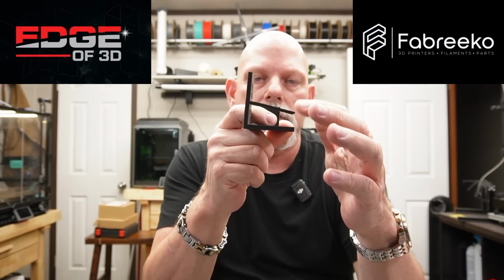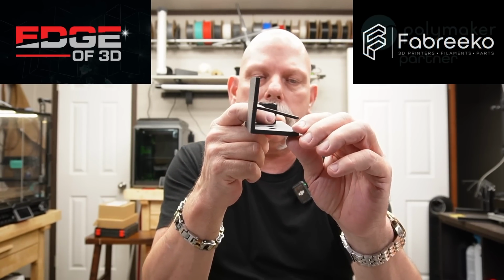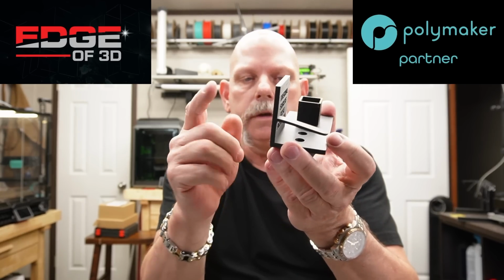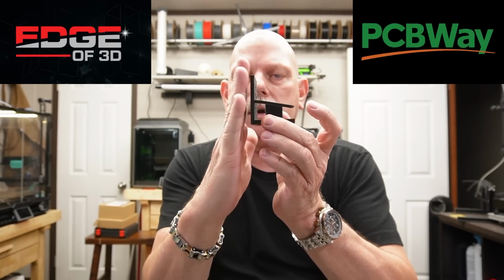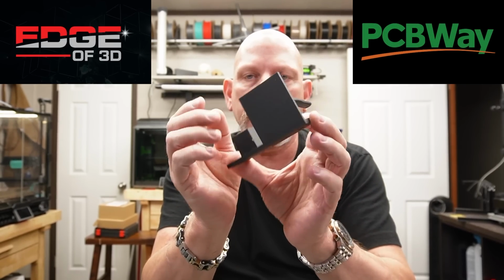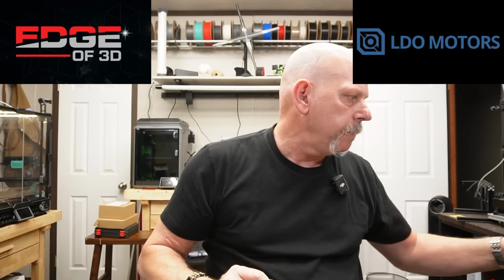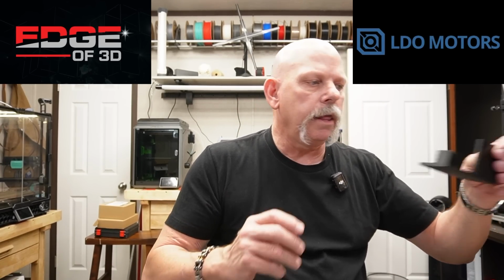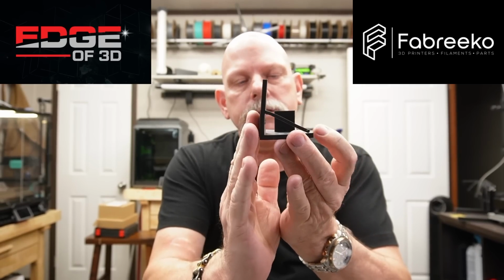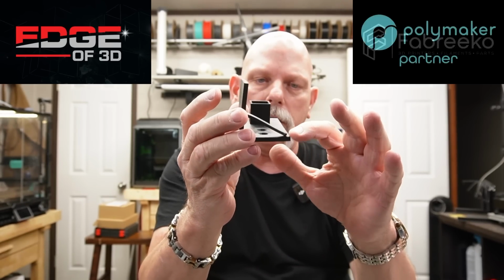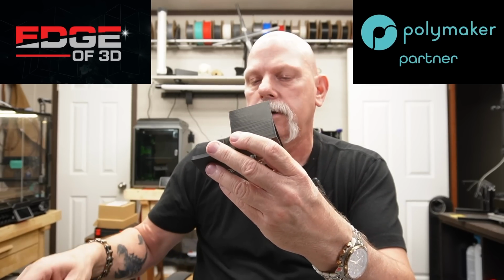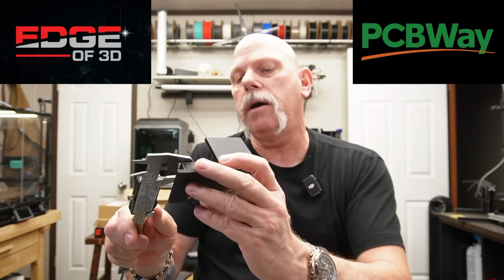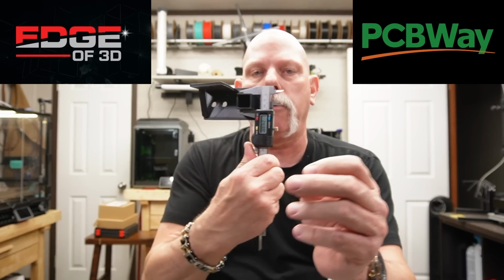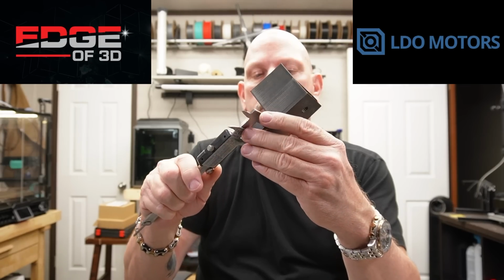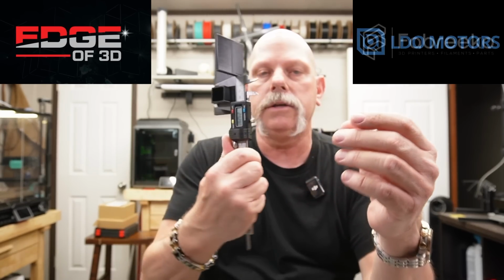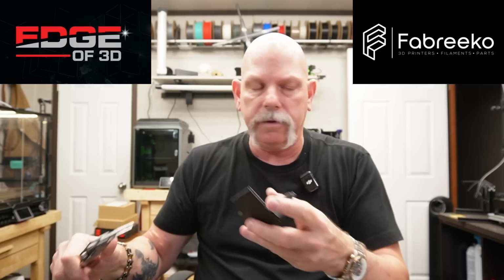And you know, the arm shrunk a little bit, but it didn't come all the way down. The back is a little bit out of kilter. It's not a 90-degree angle anymore. Silk PLA, it tipped a little bit more. This came all the way down till it's touching. The box on it wound up at 24.3, so it had a little bit more shrinkage than the Polymaker at 24.25.